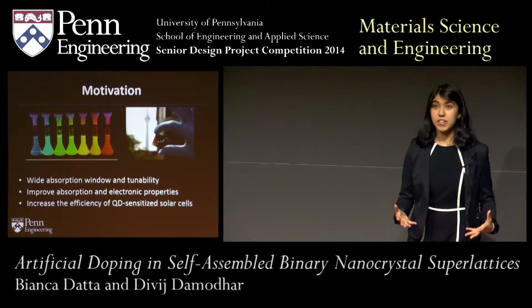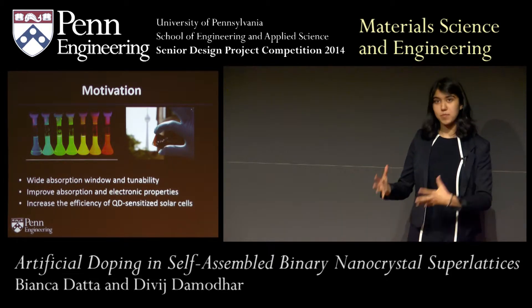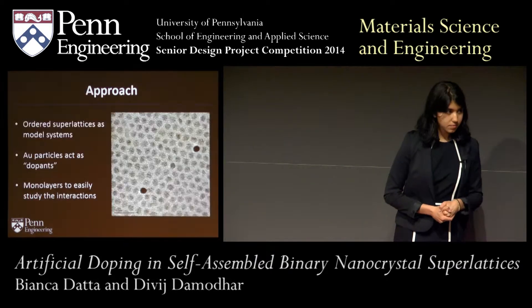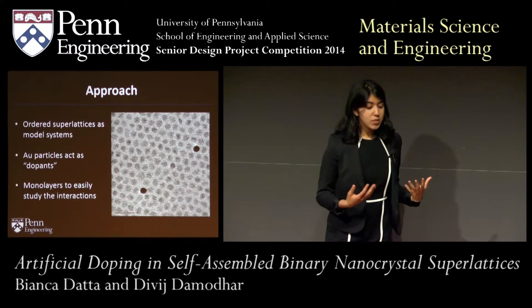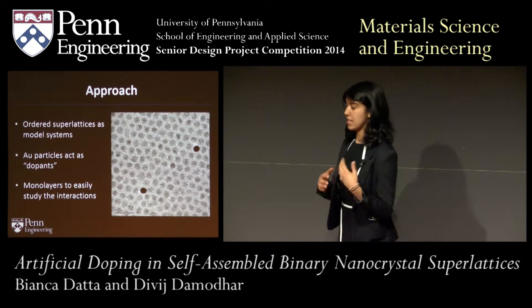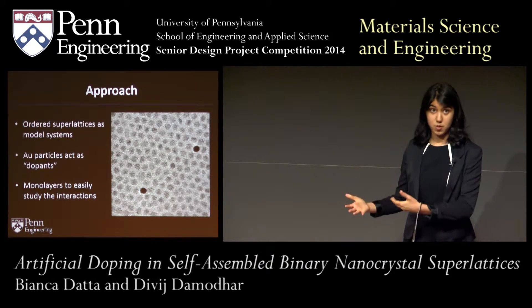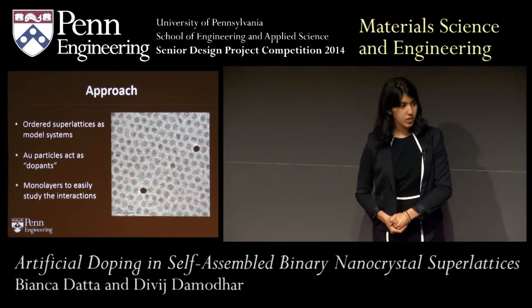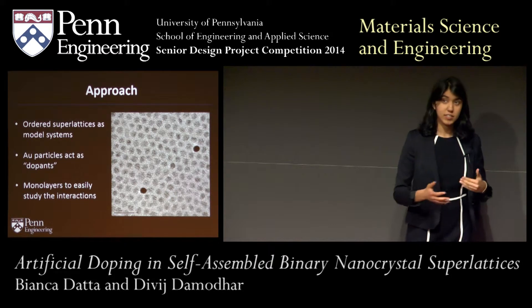While these materials have very good absorption properties, they don't have fantastic charge transport properties. So the overall motivation behind our project was to increase the efficiency of quantum dot synthesized solar cells by improving all of these properties in these systems. We went about this by creating ordered superlattice structures to model ideal systems. Coupled nanoparticle assemblies actually serve as observable models of atomic doping phenomena. We chose to use plasmonic gold particles to act as the dopants. Gold was selected because it improves the scattering cross section of the material, improving absorption properties, and it can also improve the electronic properties by improving electron charge transport. We carefully produced gold to match the size of the cadmium selenide quantum dots so it could fit into the assembled lattices.